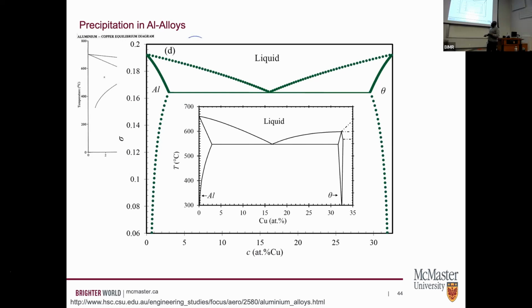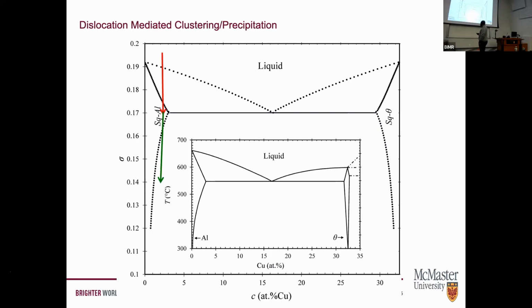And I say facsimile because no one as yet, over the course of this particular treatment of phase field crystal models, has developed a very quantitative way to map thermodynamics to this particular formulation. And so it's somewhat of a facsimile where we've tried to get the right two-phase coexistence, the right solubility, right kind of homologous temperature, and things of that nature. Okay? So what I'm going to do is take some material, and my assumption here is that defects, particularly dislocations, are what will mediate this transformation. I'm going to quench it into this one-phase region where I expect to get this polycrystalline network. And then I'm going to quench it yet again to this two-phase region where I expect the clustering to occur, picking up some of this secondary phase information as well.